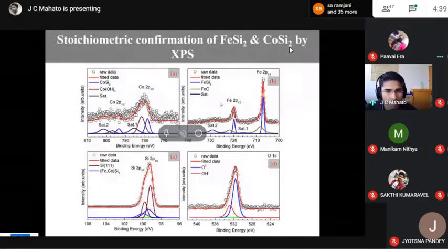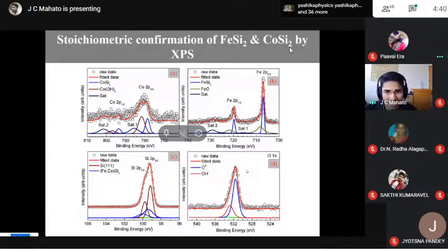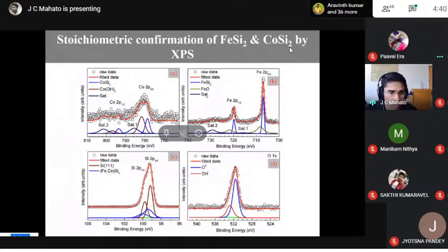So for the compositional confirmation, we did XPS measurement, and this is the cobalt 2p, iron 2p, silicon 2p, and oxygen 1s XPS data. The open circles are the data, and from this we can confirm that the cobalt disilicide and iron disilicide have been grown on the silicon 111 surface.